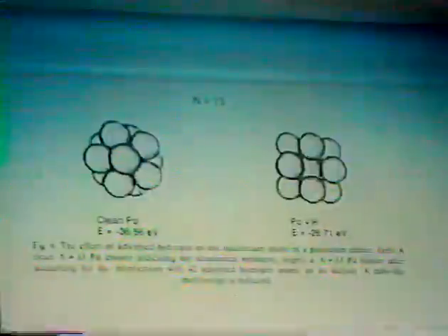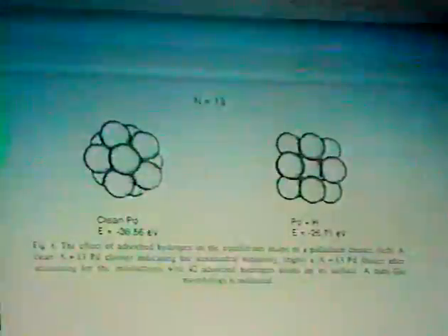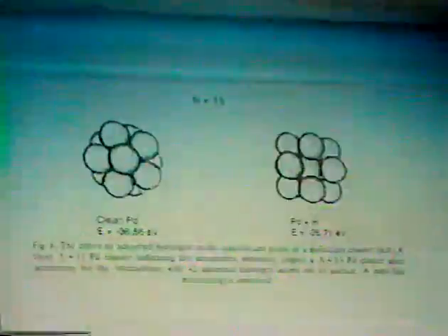hypothesizes that the reason is that these particles don't have regular shapes, and they're flexible, and they maybe are in constant motion, and therefore they don't give results of catalytic reactions that are consistent with what we would call regular shape. So this whole idea has been introduced here, and I want to show you a little bit later on how this seems to explain some of the results that we've been getting for about the last 10 or 15 years.